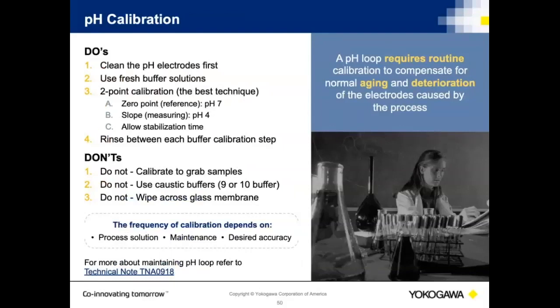Temperature. Make certain that you allow temperature stabilization. If I take a pH probe and I pull it out of the selective catalytic reactor, and that SCR happened to be at 180 degrees C, and I pull the probe out and basically want to do a calibration to buffer solutions that are at room temperature, I'm going to have an issue. I must let the probe settle down. So that 180 degrees F, I'm sorry, I said C before, I basically need to let the probe's temperature settle down to the temperature of the buffer solution. Otherwise, I will be chasing my calibration.